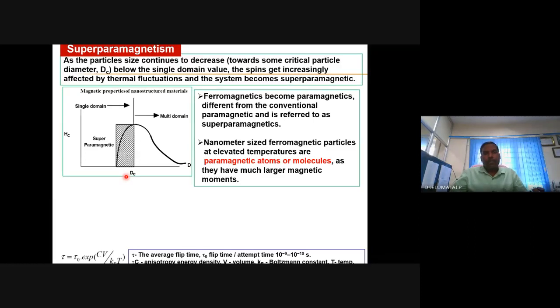When can this happen? Again, this is material dependent. For ferromagnetic materials, until you reach the grain size Dc, known as the critical dimension or critical diameter, the material will show the usual ferromagnetic behavior or any other magnetic behavior. Once the grain size is reduced down to Dc, ferromagnetic materials are transformed into superparamagnetic materials. This is the difference between bulk and nano. And the magnetic momentum of these superparamagnets is exceedingly high compared to conventional paramagnetic materials. We call such magnetic materials superparamagnetic atoms or molecules.